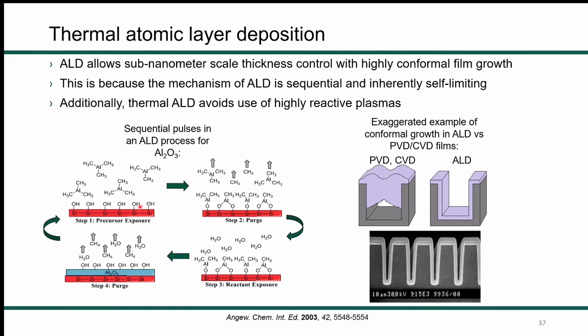In the general ALD scheme, I'll show the reaction between trimethylaluminum and water. In an ALD process, the first step is introducing a precursor to the desired substrate — in this case silicon — where the ALD precursor reacts with every available surface reactive site, saturating the surface. The second step is a purge using inert gas to remove excess precursor and reaction byproducts. The third step is introduction of a second reactant, which again reacts with every available surface site in a self-saturating manner. The fourth step is a second purge, and you can repeat this for any number of cycles to get the desired film thickness.